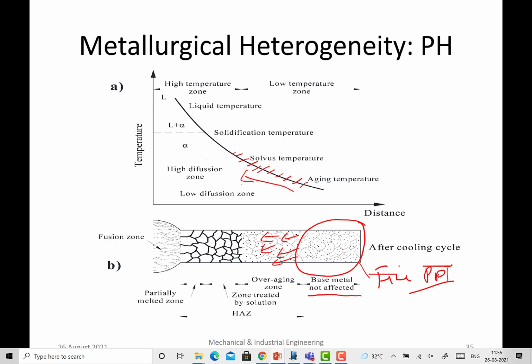There are two things which are possible. Because it was strengthened by the precipitation hardening, you have already got it aged to such an extent that there are sufficient precipitates. The further heating to the higher temperature for longer time will be causing the overaging. Overaging means the loss of certain precipitates and coarsening of the existing precipitates. These are the two changes that will be occurring. And further higher temperature will be leading to the complete dissolution of these precipitates. Okay, so there are three changes which are taking place. Initially you have the base metal having the fine precipitates, then these are getting overaged, then these are getting dissolved. Okay, and you are left with the homogeneous coarse grained alpha matrix only. All precipitates have got lost.